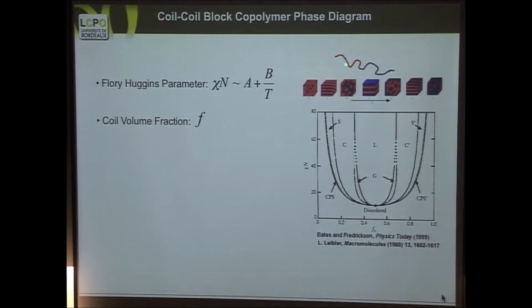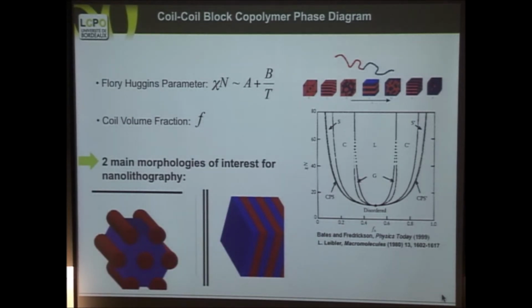The chi is the interaction parameter between the red and the blue block. N is the degree of polymerization, which represents the entropy. Entropy makes the Gibbs free energy, and you have the composition. And you see, by playing with these 3 parameters, we can have structures that are lamellar, or cylindrical, or bicontinuous. The bicontinuous we will find a good use for in photovoltaic devices, but the lamellar and the cylindrical we can find a good use for in these nanotechnologies of the bottom-up type of nanofabrication.